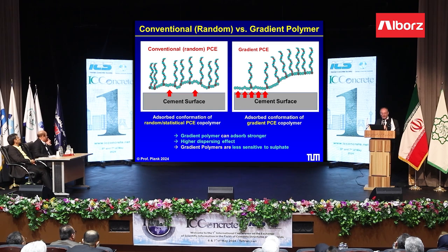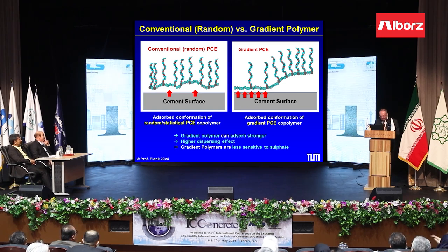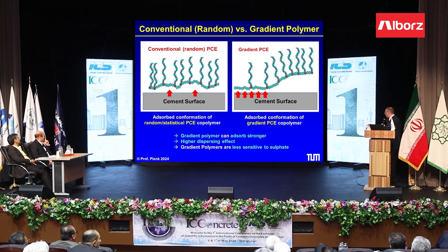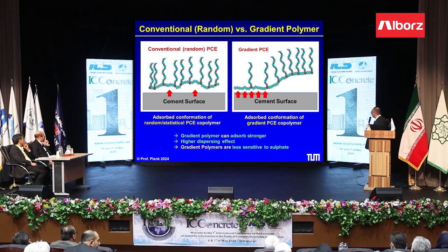Now, briefly, because of the time, I hope it's okay, thank you, just about some very new developments. When we polymerize PCEs, normally we get what we call a random or statistical distribution of the side chains along the main chain. And such a molecule has a limited ability to interact with the cement surface. But if we can make a gradient polymer where we have some blocks of carboxylate groups here, then the interaction is much stronger and we have a more effective molecule.